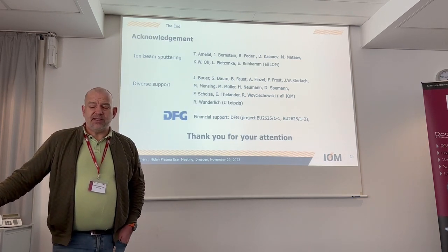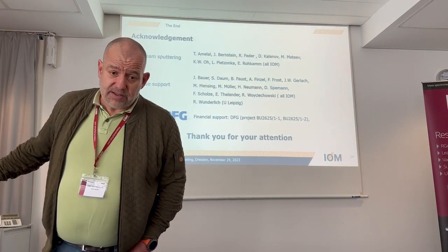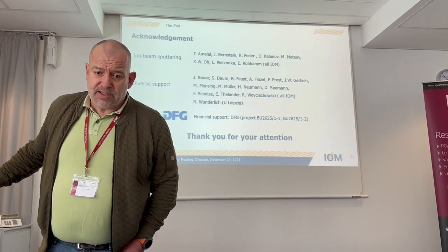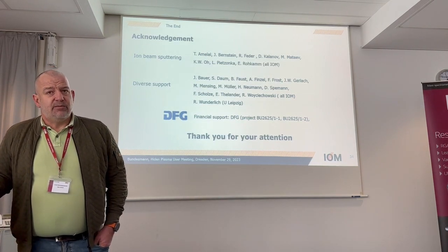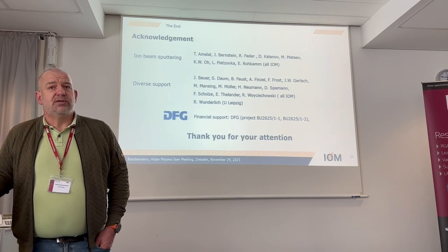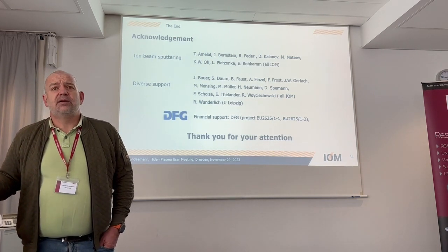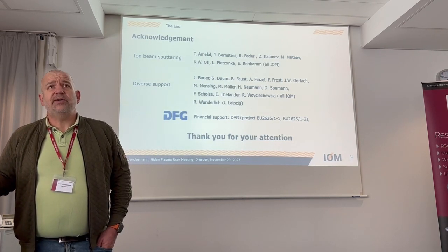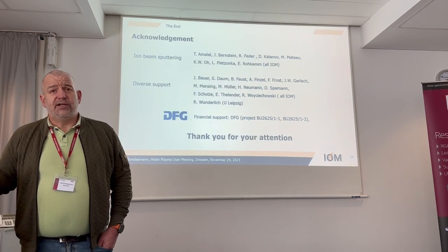So we were testing it with another device, and we are able to measure post-ionized secondary atoms up to about 100 electron volts. And then we figured out that the intensity was too low to measure anything. But what we did is we ran some TRIM-SP simulations, and they showed very similar shapes, so we are quite sure that it's a similar shape for the atoms as well.